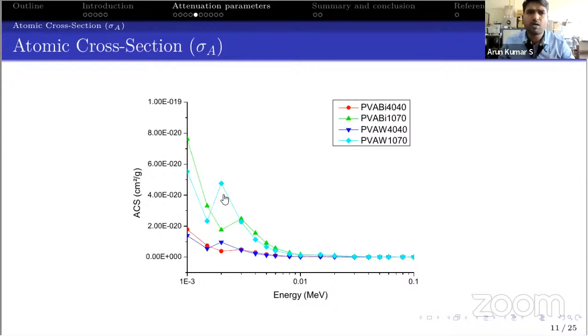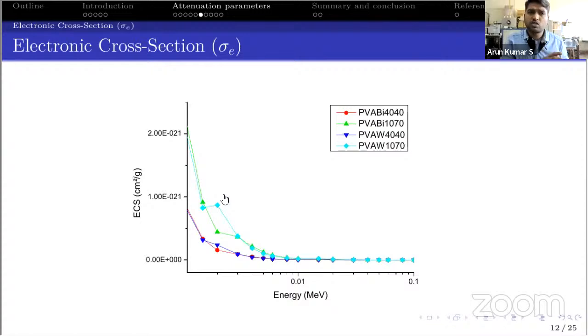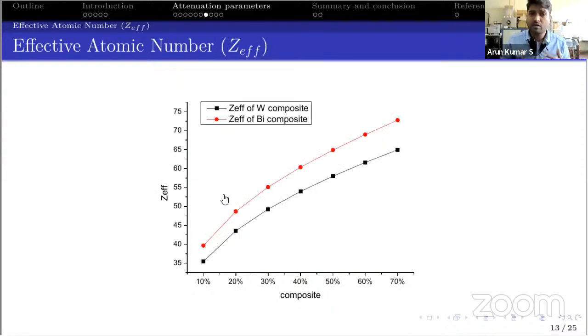Let's go further. Here I'm observing the electronic cross section of the material, and it is also giving a similar pattern, and there is not much difference. And here I have taken the effective Z of the material. Here you can observe clearly the tungsten PVA composite has lower Z effective when compared to the bismuth PVA composite. It's quite natural because bismuth has a high Z when compared to tungsten.